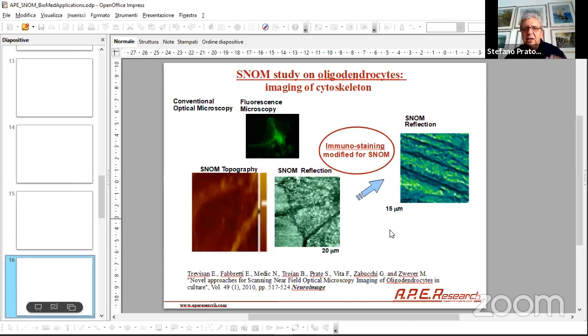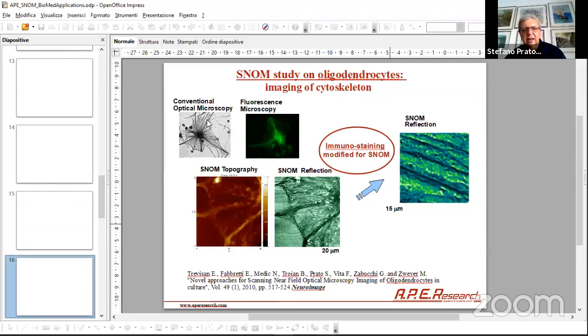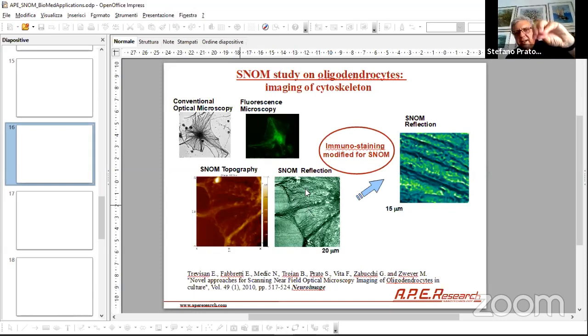Plus, if you want, you can induce some more evident contrast. Again, here we have a cell, and this is the topography. In this case we stained with some dye, so it's like painting the molecule. In this case you want to see these microtubules here. This dye has a special link that attaches exactly on some tubular structure that we expect to measure. So this is the topography, and this is the color, I would say, with a scale that is below the diffraction limit. This is a combination, again, I repeat, of AFM plus optical imaging at the nanoscale that is called SNOM, scanning near field optical microscope. So this is a conventional AFM and this is SNOM.